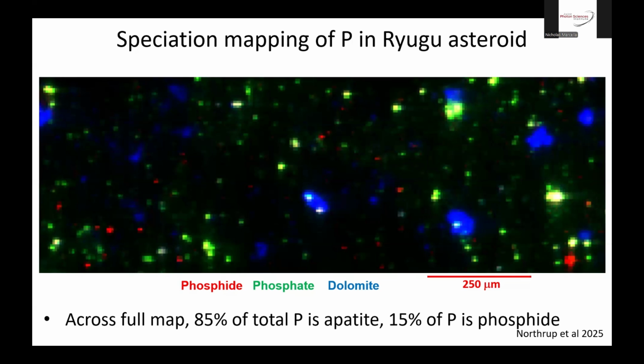And we can map that, and by integrating the area, we calculate that 85% of the total phosphorus is in the form of apatite, and 15% is phosphide. And this has important implications for the formation conditions, the redox state of the formation conditions of this asteroid 4.7 billion years ago. So that's a pretty interesting result.